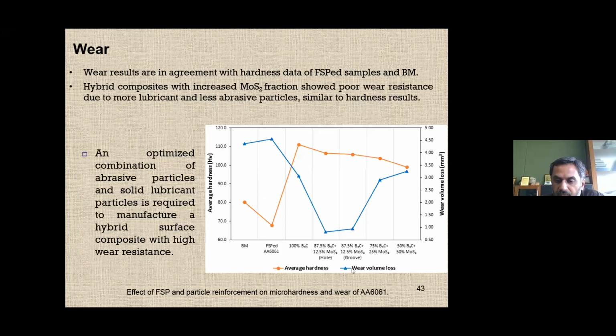You see the blue indicates the wear volume loss. You see, this is your base metal. Then you do FSP, which is 3 passes without any addition. You see the 100% B4C. There is a drastic reduction in the wear, right? And then you see, if you add instead of 50%, you see here, you have 12.5% MoS2, which has the least wear, which is very good, right? Hole method and slot method. But the moment you have 25% MoS2, you see the wear has further increased. 50-50 has the highest. So what we found is that 12.5% MoS2 is the best composition, whether it is a hole method or a slot method. Hole is more preferred because it has the least wear compared to the groove, a minor difference.